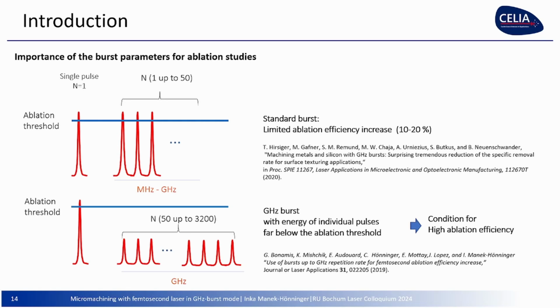And we are in a regime where each individual pulse within the burst is below the ablation threshold. So that means you need lots of pulses, many more. One is not really a burst, but from 2 you can talk about a burst. From single pulse to 50, you see these strange effects. And here, in this regime, this is totally different, because with a single pulse of the burst, you wouldn't ablate at all. And these were the studies that I will show you later on for the ablation efficiency that we saw.